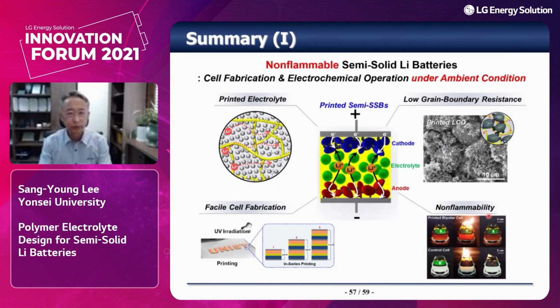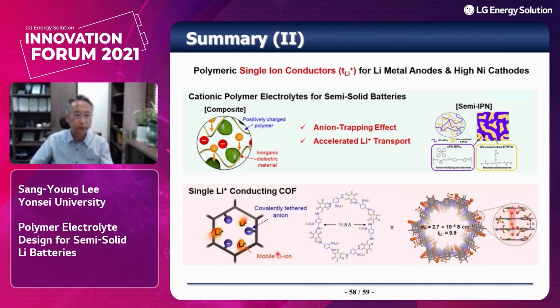Okay, let me conclude my talk with a brief summary. In this talk, I have demonstrated non-flammable, semi-solid lithium batteries, which can be potentially viable in terms of commercialization. More importantly, the cell fabrication and electrochemical operation can be achieved under ambient conditions. The second part was devoted to polymeric single lithium-ion conductors. The interesting finding is that these polymeric single-ion conductors can show stability with the lithium metal anode and, more importantly, with a high-nickel cathode.